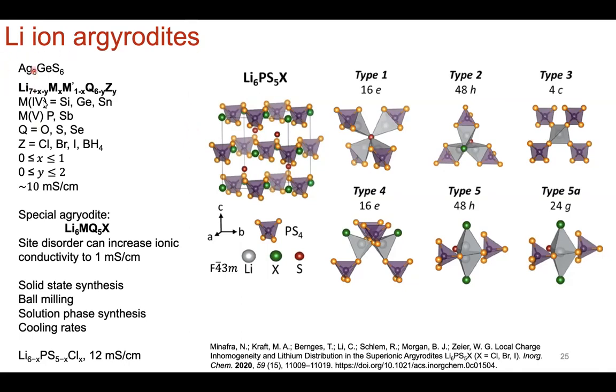You can change the lithium ion concentration, which we've seen can increase the ion conductivity by stuffing the system. You can play around with site disorder with cation substitution. So here you have a tetravalent element like silicon, germanium, tin, or pentavalent species like phosphorus or antimony. And then the anions could really be all of this. Could be an oxide, could be a sulfide, could be a selenide mixed in with halides and even borohydride. I mean, it's very exciting.